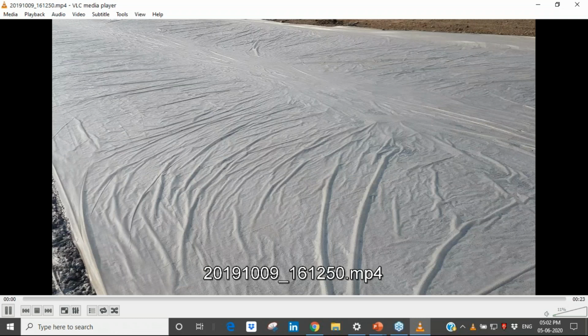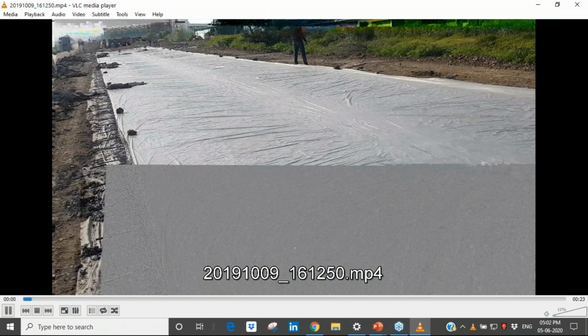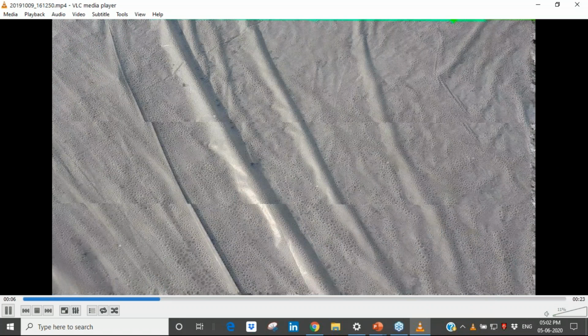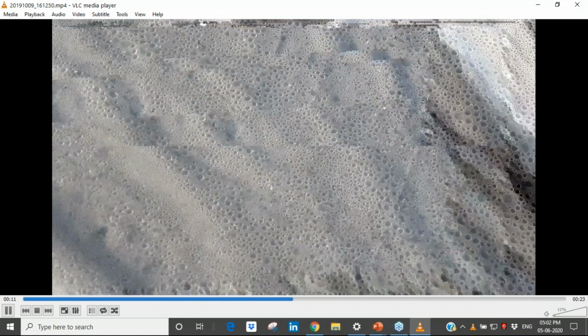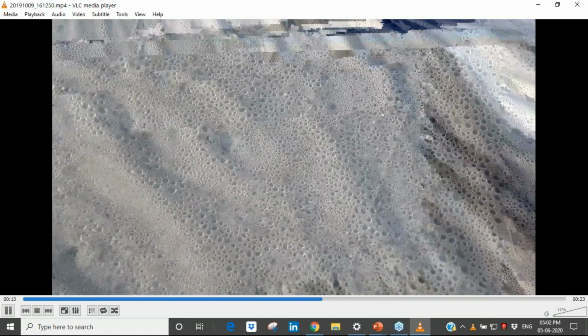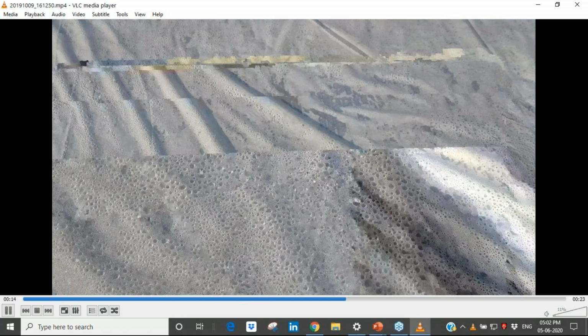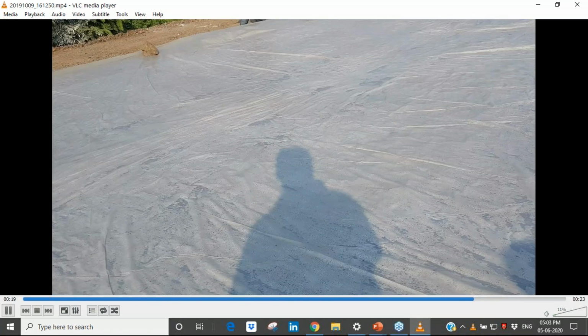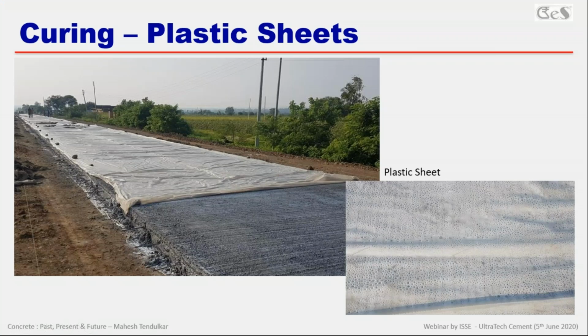immediately after spreading curing compound. You can see this picture, there is a slight problem with the video, but you can see we spray this compound and the curing compound dries within 30 to 45 minutes. This is placed. So we protect the concrete within 2-3 hours after placing, and absolutely this road has zero cracks because it is protected with plastic sheet.